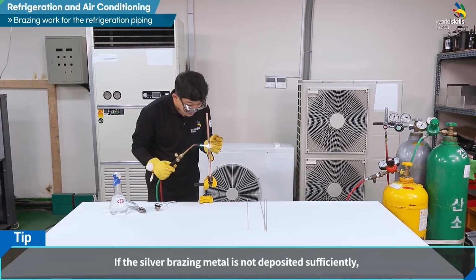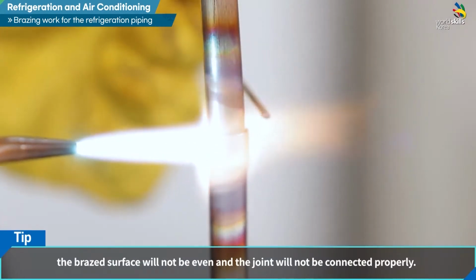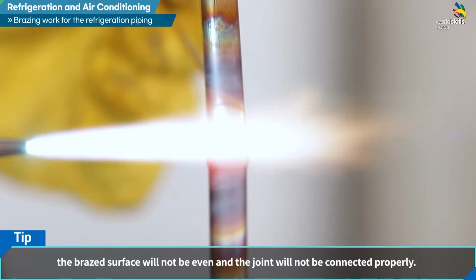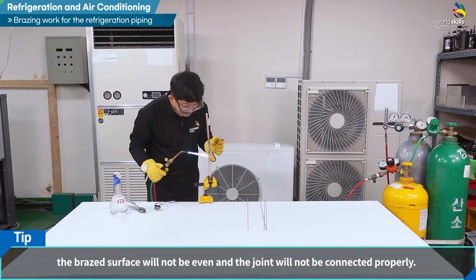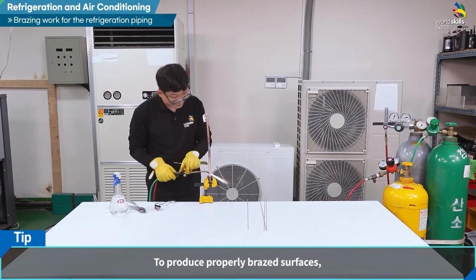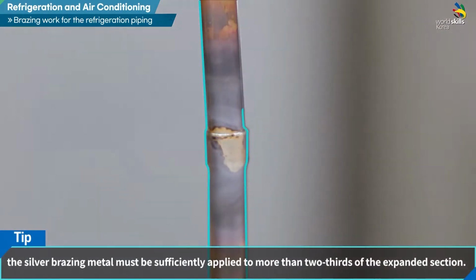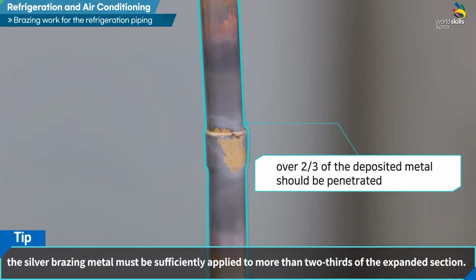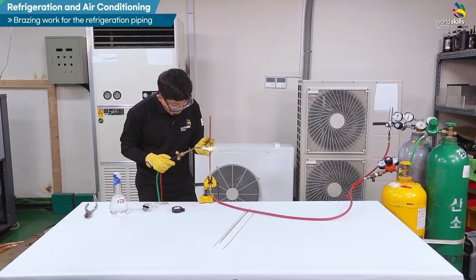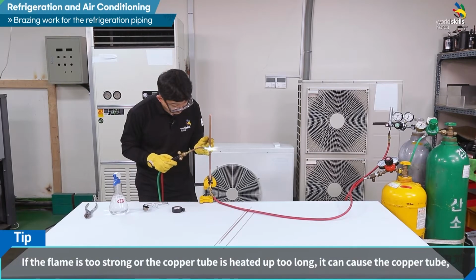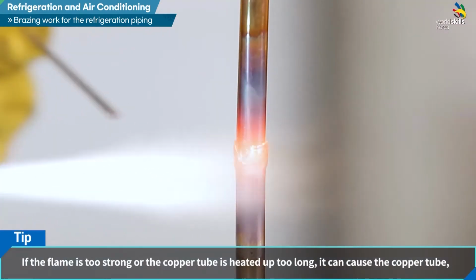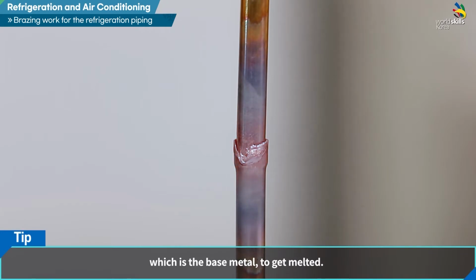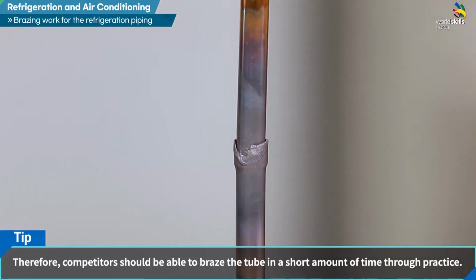If the silver brazing metal is not deposited sufficiently, the brazed surface will not be even and the joint will not be connected properly. To produce properly brazed surfaces, the silver brazing metal must be sufficiently applied to more than 2/3 of the expanded section. If the flame is too strong or the copper tube is heated up too long, it can cause the copper tube, which is the base metal, to get melted. Therefore, competitors should be able to braze the tube in a short amount of time through practice.